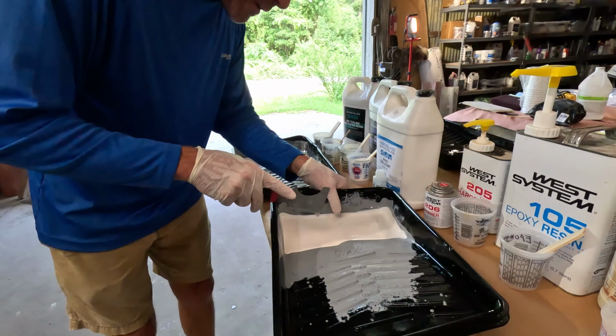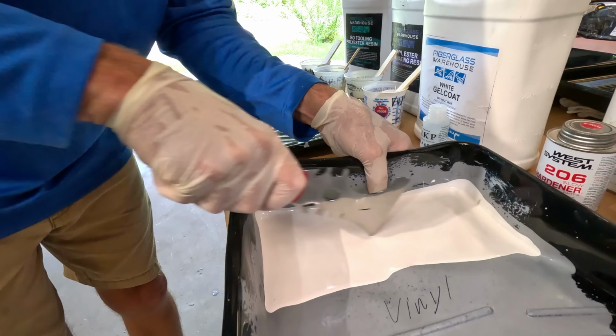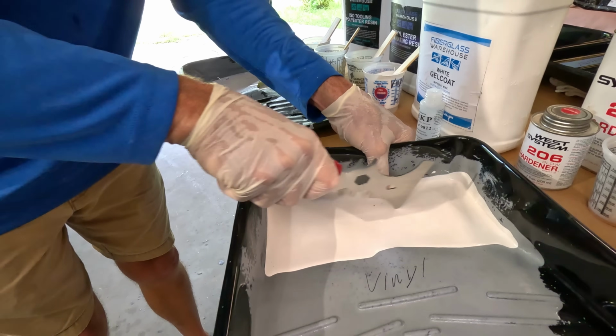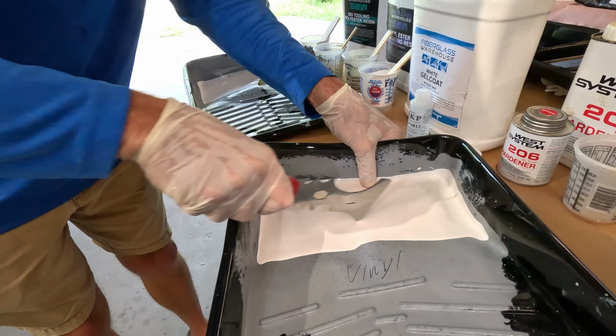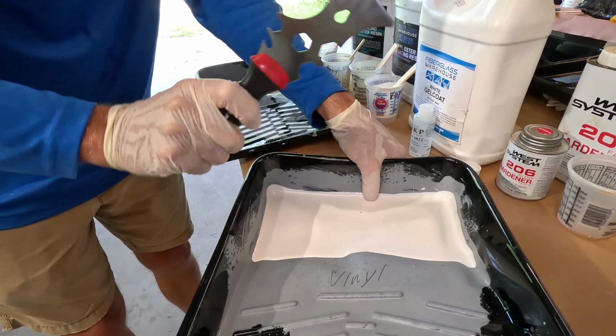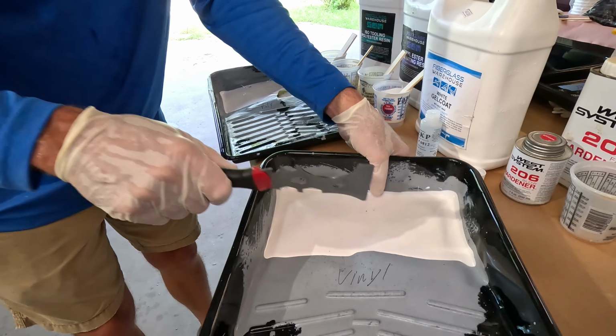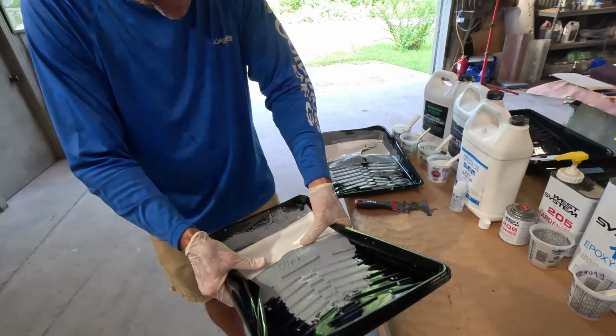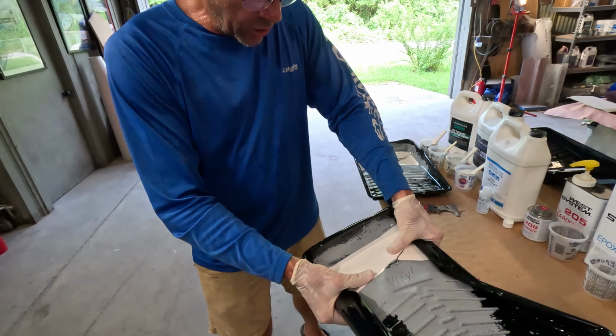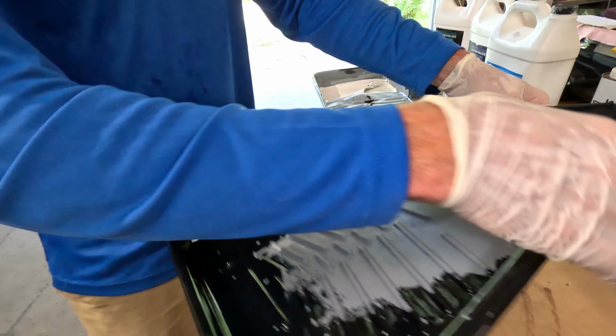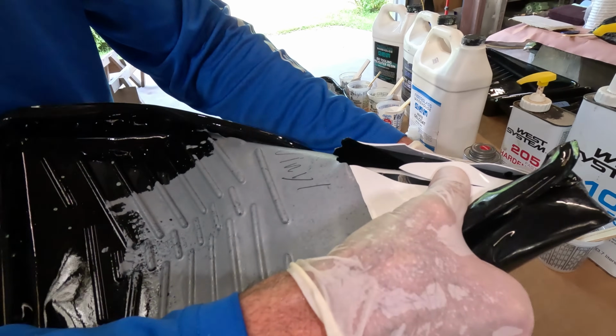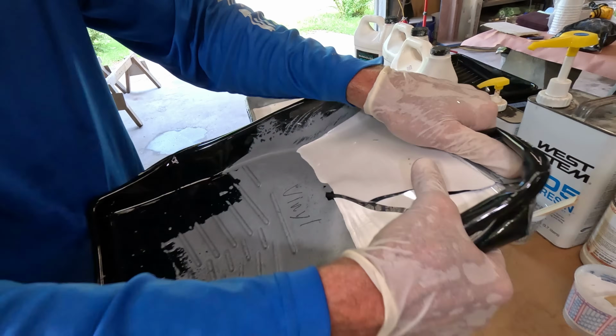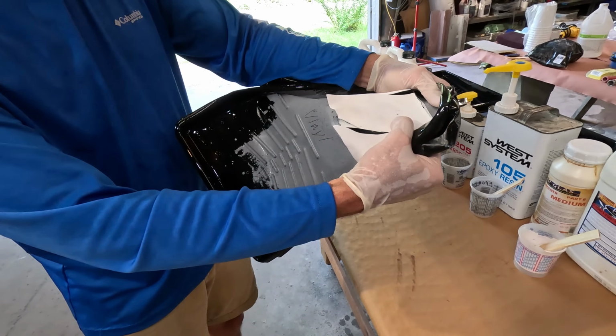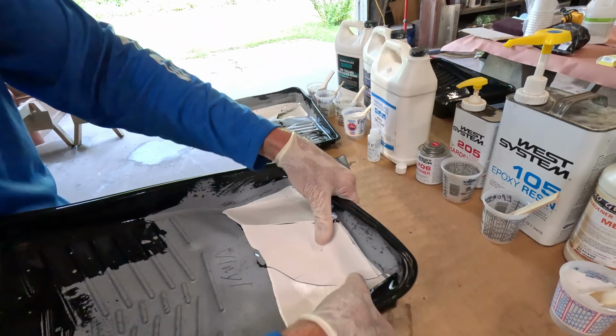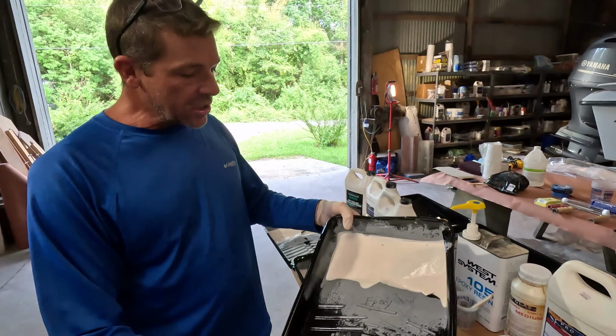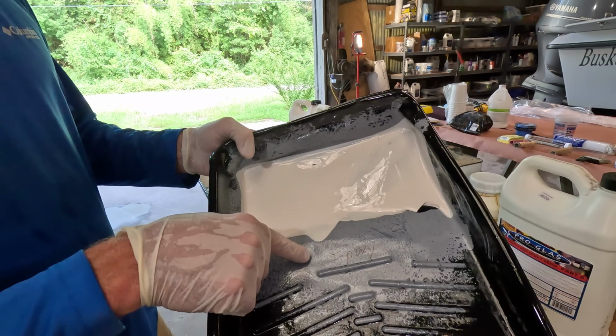So, with the vinyl ester, same deal. If we're using our little 5-in-1 tool, very minimal scratching. It seems to be quite tough. There's a crack. It's nice and crisp, kind of what you would expect. Appears to be fully cured in every way. So this is the one that we did with epoxy.